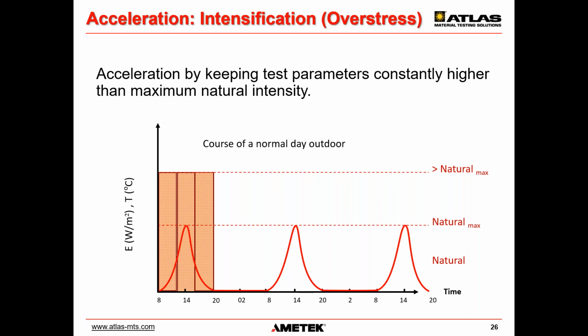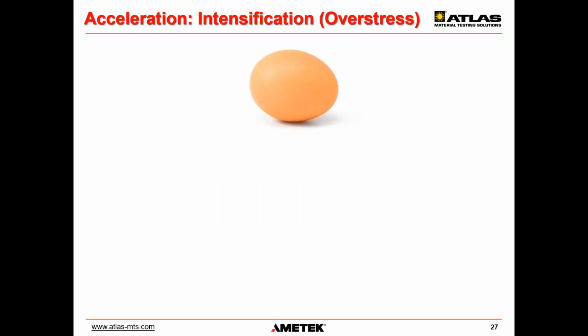Just realize that there are practical as well as scientific limits to the amount of overstress we can use without affecting the correlation. The same is true with time compression by eliminating chemical processes that occur in the dark, as well as eliminating temperature cycling and its effect. So be careful. The higher the acceleration factor, the higher the risk for non-correlation.